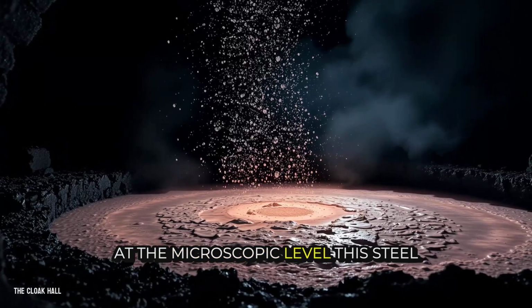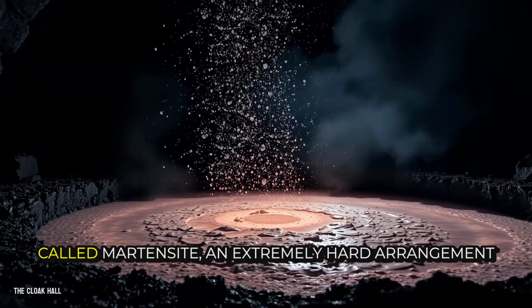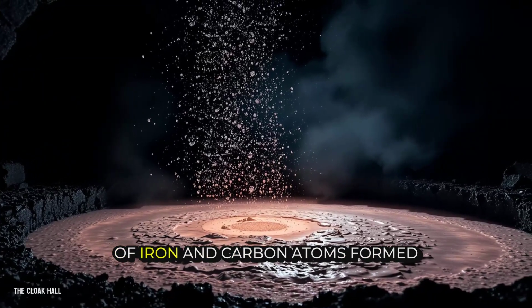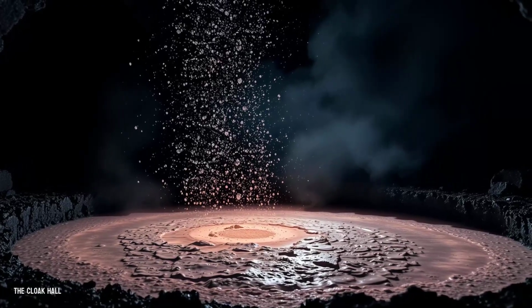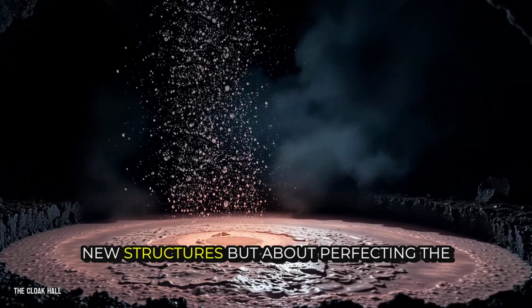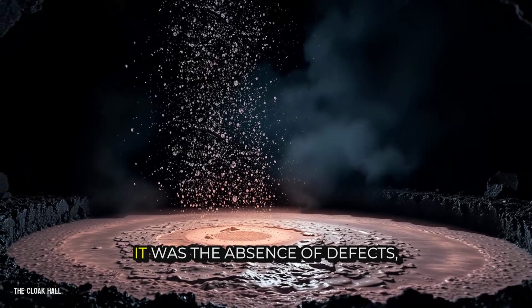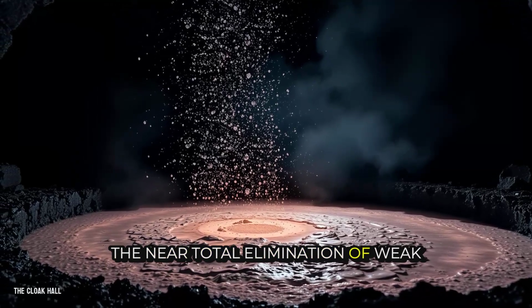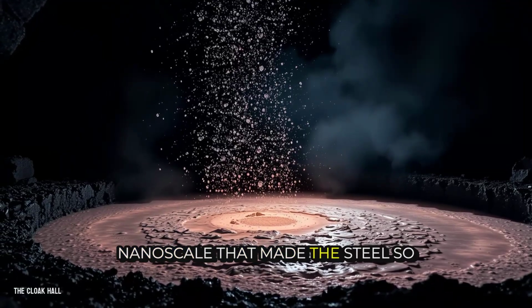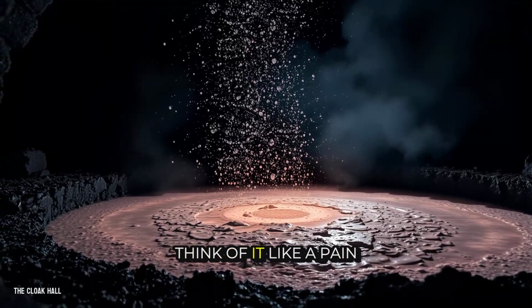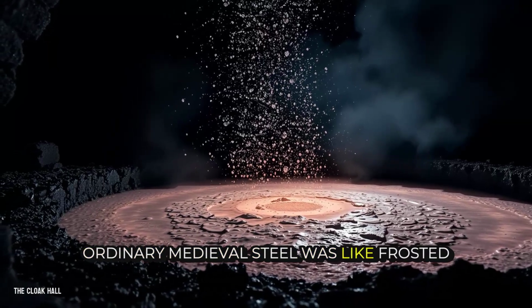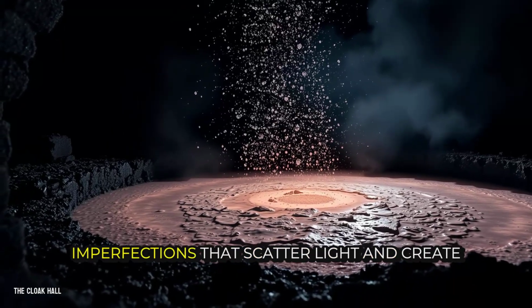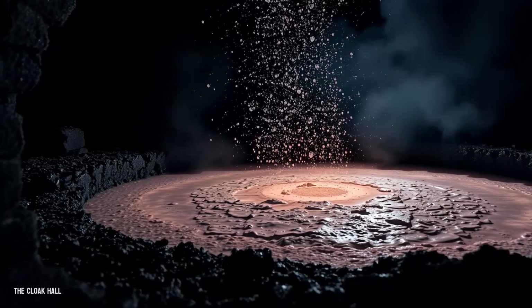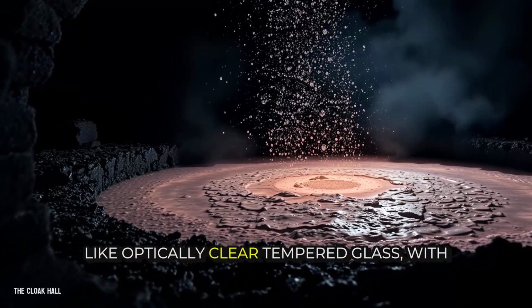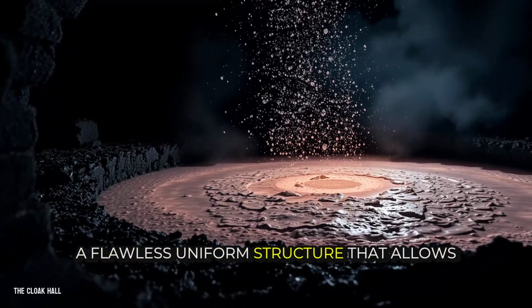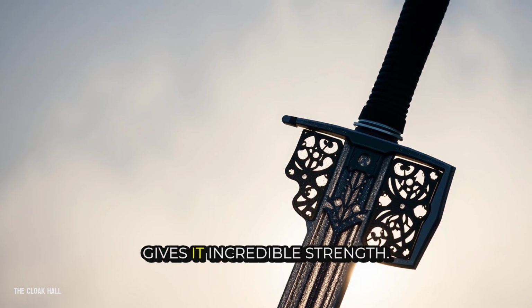At the microscopic level, this steel was composed primarily of a structure called martensite, an extremely hard arrangement of iron and carbon atoms formed by that masterful quench. The nanotechnology here wasn't about adding new structures, but about perfecting the foundation itself. It was the absence of defects, the near-total elimination of weak points at the micro and even nanoscale that made the steel so extraordinary. Think of it like a pane of glass. Ordinary medieval steel was like frosted glass, full of tiny bubbles and imperfections that scatter light and create weak spots. The Ulfbert steel, by contrast, was like optically clear, tempered glass, with a flawless, uniform structure that allows light to pass straight through and gives it incredible strength.